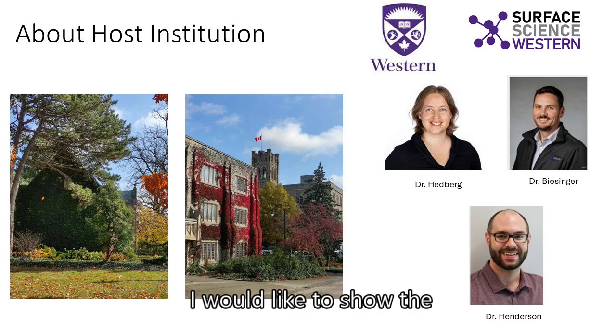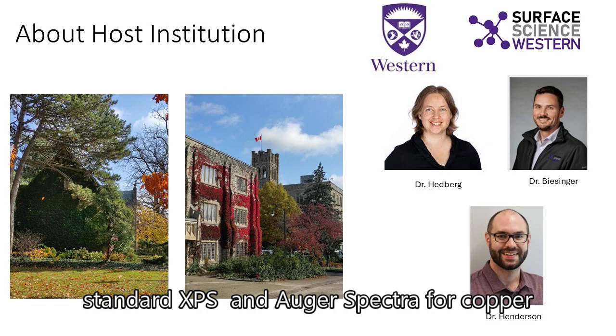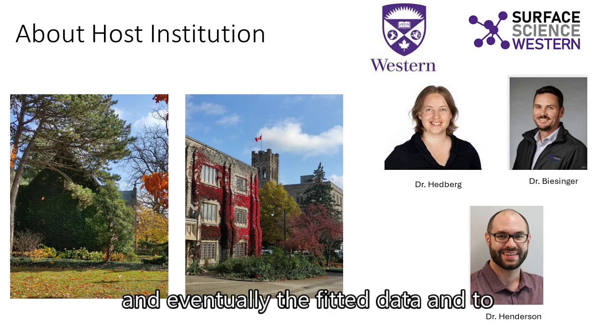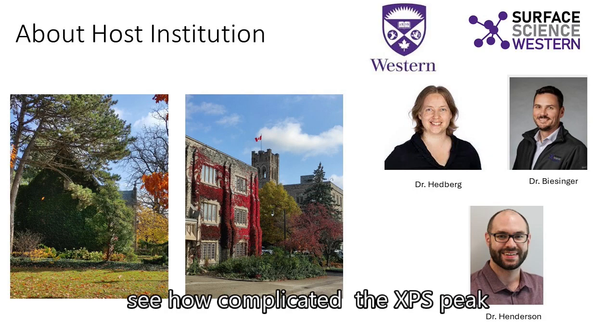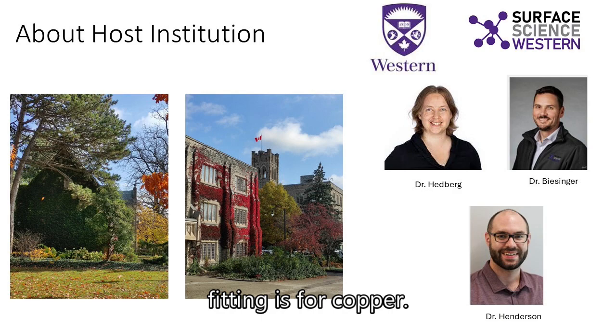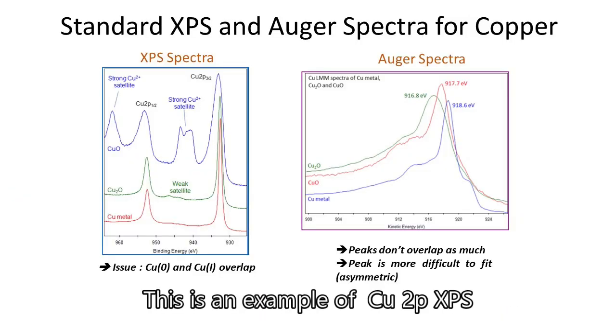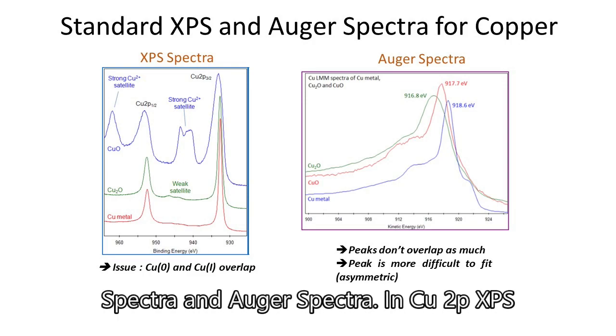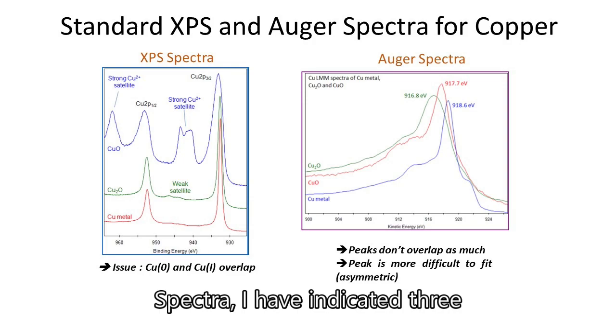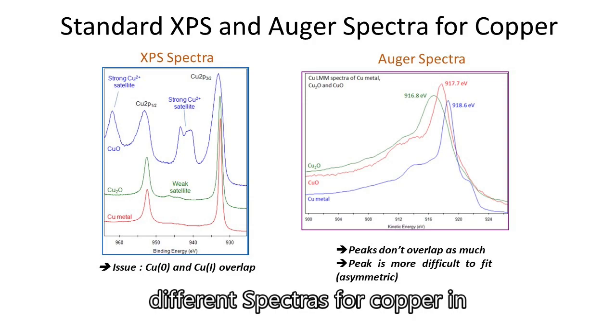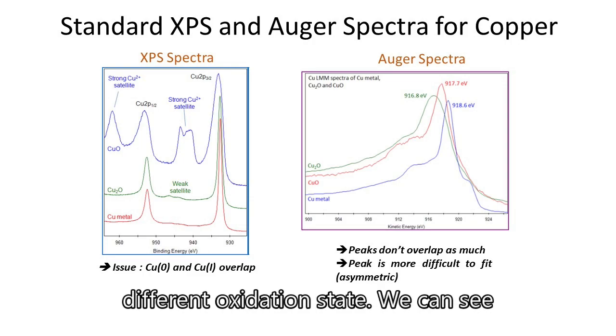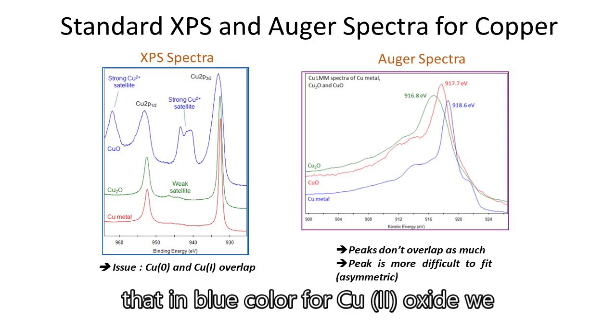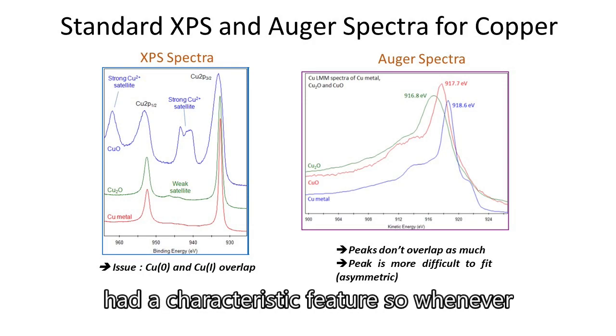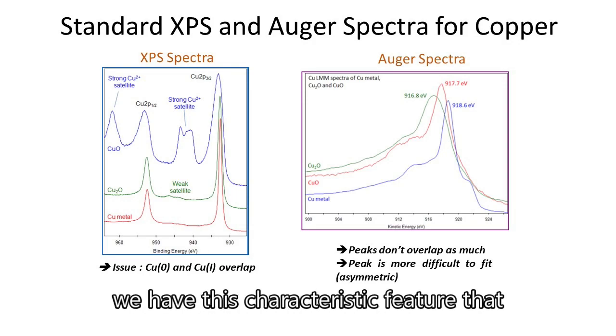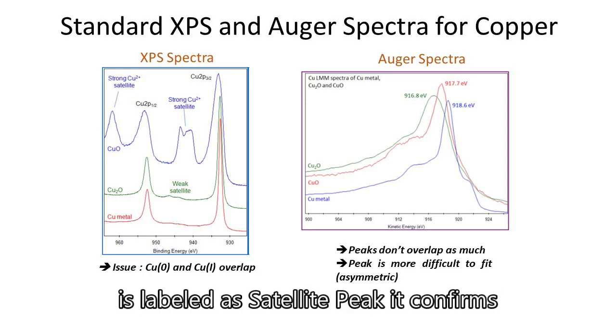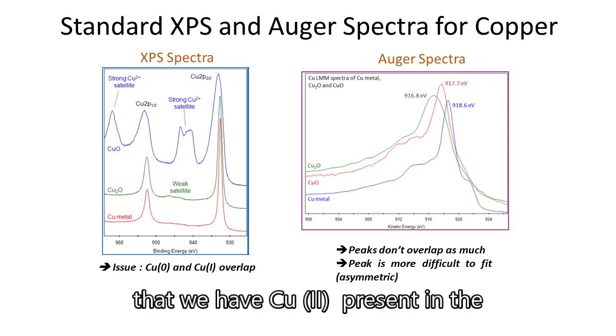I would like to show the standard XPS and Auger spectra for copper and eventually the fitted data, to see how complicated XPS peak fitting is for copper. This is an example of copper 2p XPS spectra and Auger spectra. In the copper 2p XPS spectra, I have indicated three different spectra for copper in different oxidation states. We can see that in blue color for copper 2 oxide, we have a characteristic feature. So whenever we have this characteristic feature that is labeled as the satellite peak, it confirms that we have copper 2 present in the system.